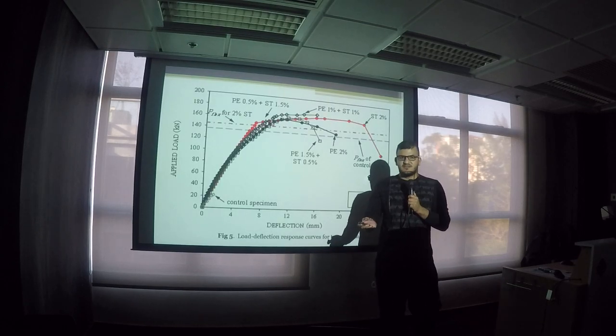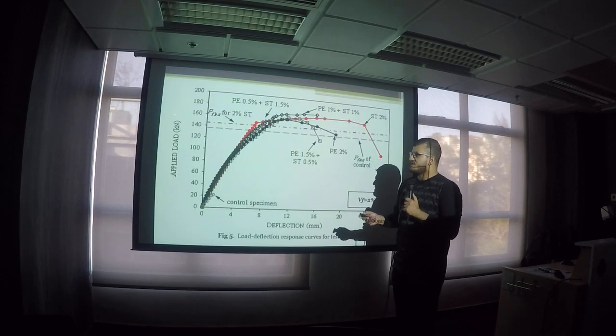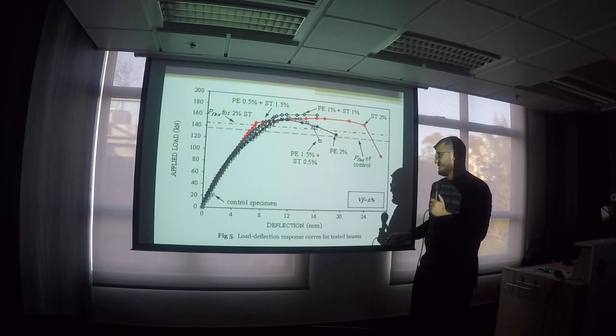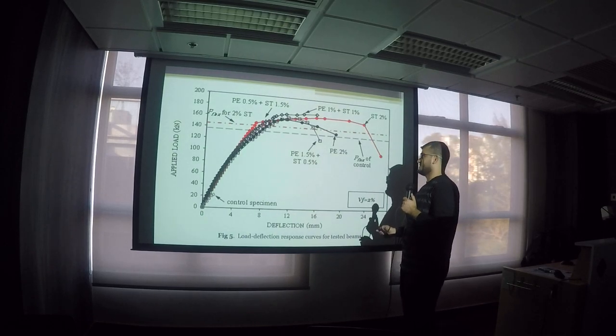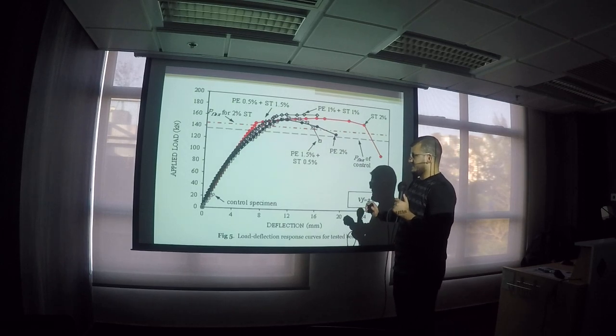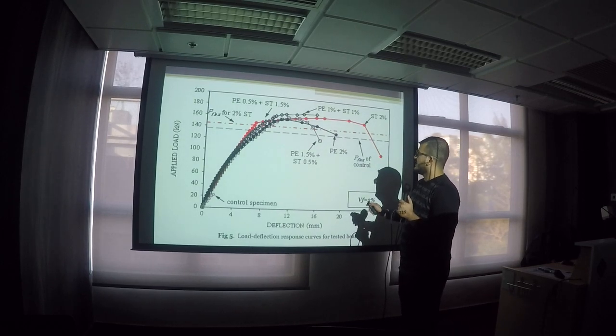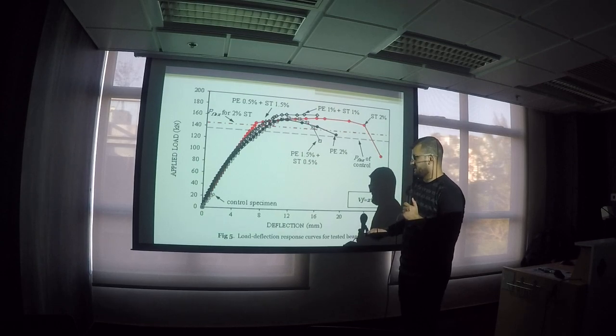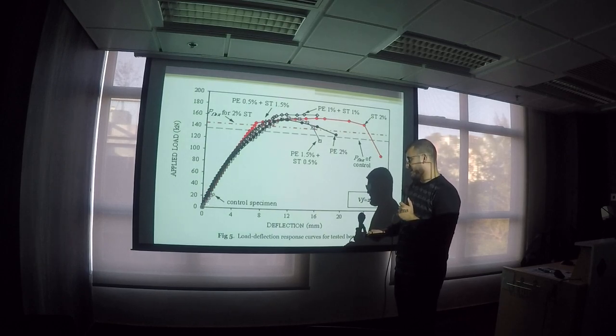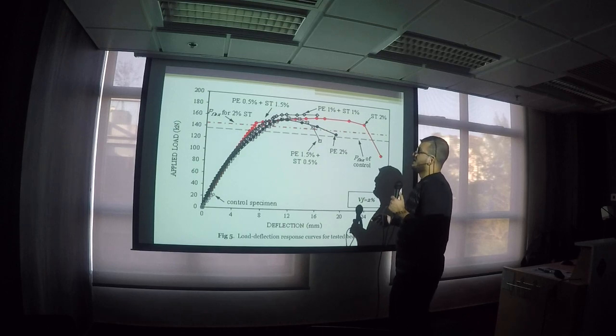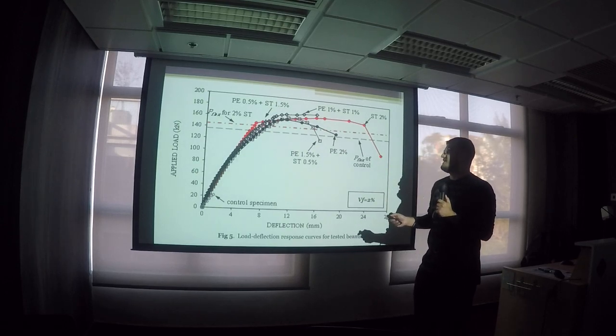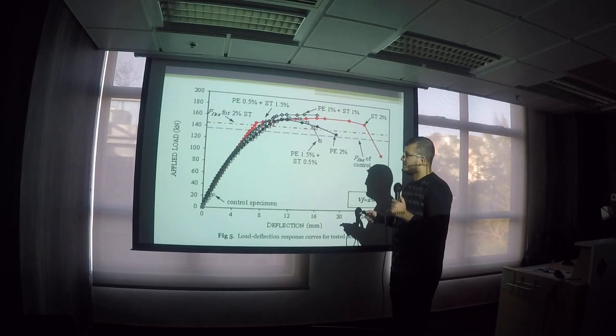This is the response curve. It's been drawn as the relationship between the applied load and the deflection. It means the load deflection curve of the specimens. At first, if you want to compare, these are the hybrid beams, and here at the end you have the control specimen. So first, the stiffness of all the hybrid beams was higher relative to the control specimen. This is number one. Number two, we can also see that increasing the steel fiber and the steel in the beam slightly increases the stiffness of such a beam.